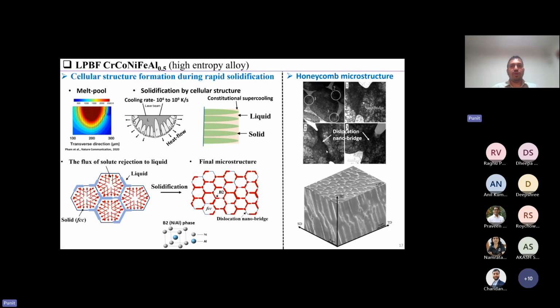So during additive manufacturing, when you are printing the material layer by layer, the layer below the layer you are melting also goes to really high temperature and expands, and when they cool down they contract. And due to this thermal cycling, you form a lot of these dislocations, and the aluminum on the cell boundary traps these dislocations. So essentially what you end up with is this cell boundary where you have these B2 phases, and these B2 phases are connected by these dislocation nano bridges.